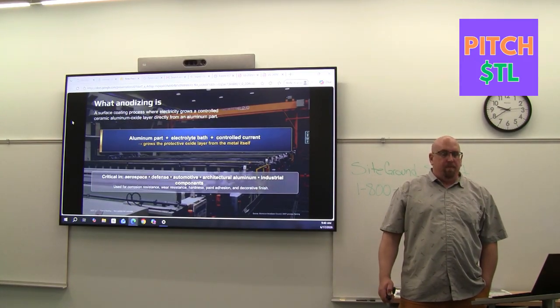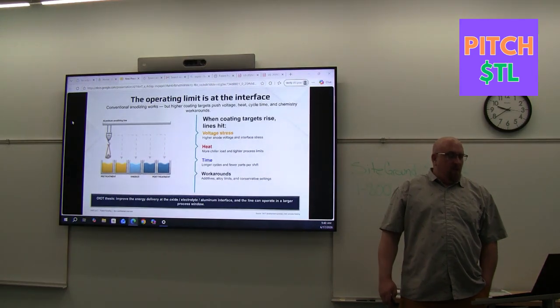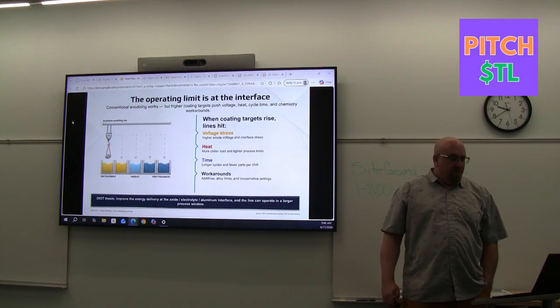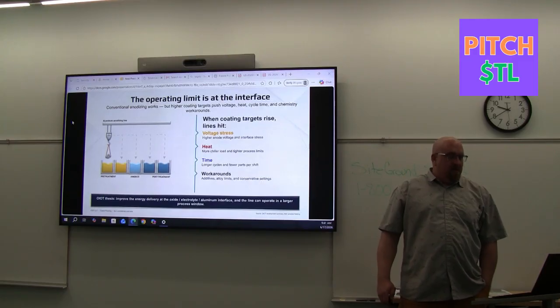high-value manufacturing. Conventional anodizing works, but it has limitations. As the coating thickness increases, so do voltage, heat, and electrical stresses. These compound the likelihood of burning, discoloration, or inconsistent oxide coating. To manage this, facilities run slower, cool harder, use chemical additives, or stay inside conservative process windows. These choices protect quality, but they reduce throughput and increase cost.